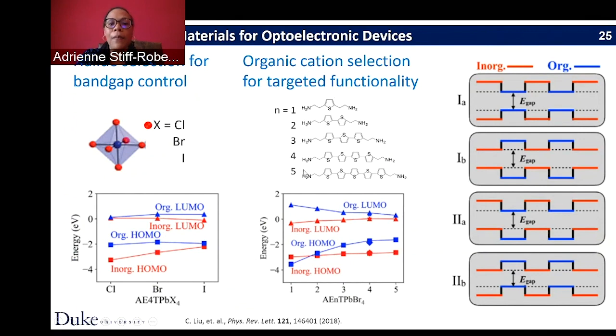So this is showing examples of one of these large organic molecules that can interrupt that 3D framework and give you a self-assembled quantum well of organic and inorganic layers. These are made up of different numbers of thiophene rings in this large molecule. And so then we have the metal halide octahedra, and they can have different metal halides. So it could be chloride, bromide, or iodide.